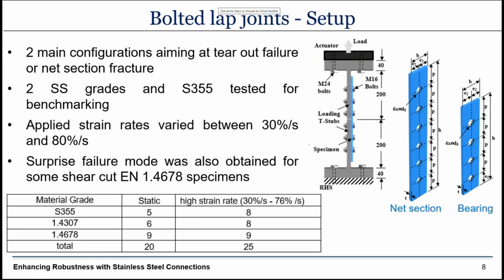So moving on to the behavior of bolted lap joints, having obtained the material coupon, we proceeded to testing lap joints under various configurations and loading speeds. The setup is shown on this slide, and the employed instrumentation included mainly digital image correlation, which allowed us to record full field strains and strain rates. The main failure modes we were targeting were bearing or tear out failure and net section fracture.